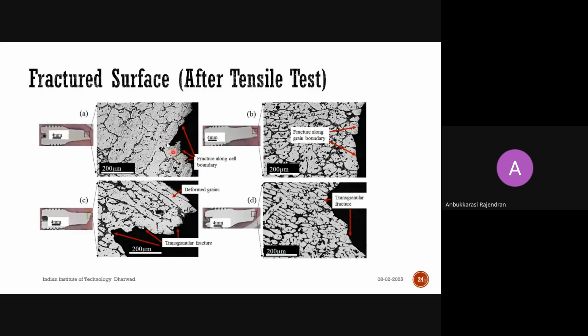We could see the fracture at the interdendritic region, where these needle-shaped intermetallics are the eutectic phase, where we can see the needle appearance. That was the crack origin point, and propagation also happened along that. To ensure that, we cut horizontal samples and polished them, a regular microstructural analysis. As it is a cast sample, it didn't require the etching process, because these eutectic phases can be revealed even in the as-polished condition itself. So we did the analysis this way.